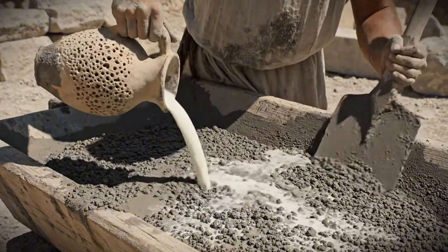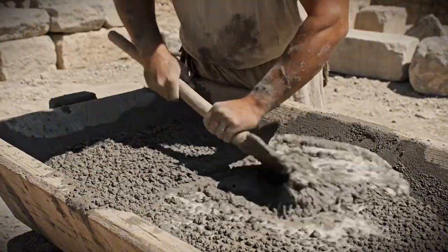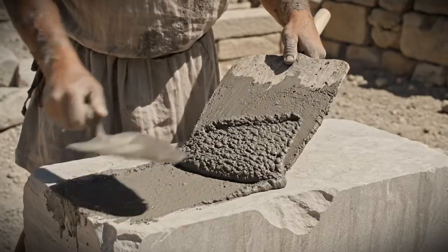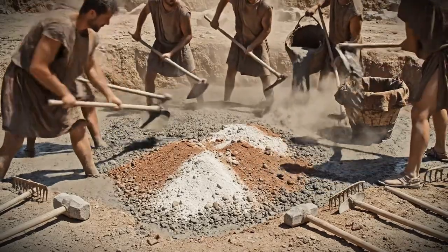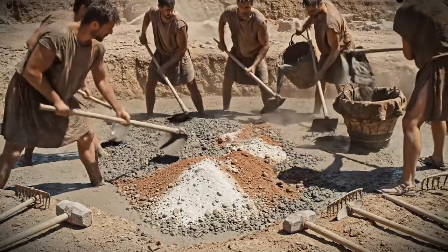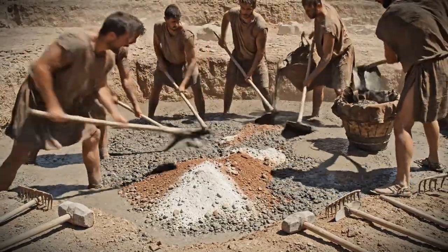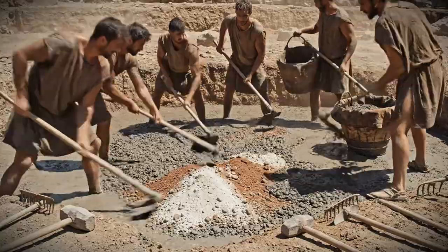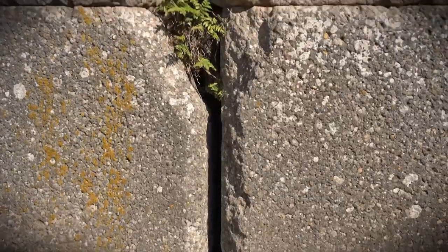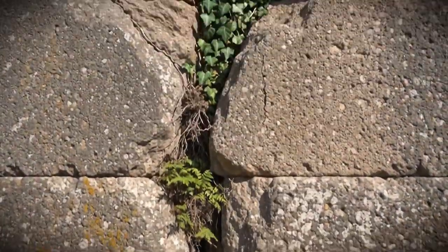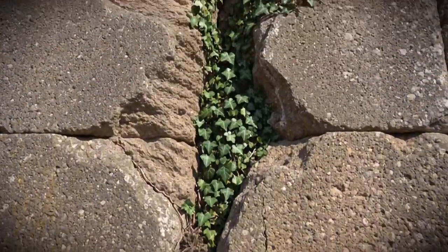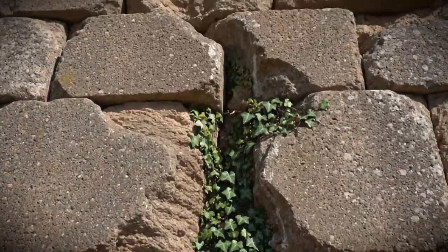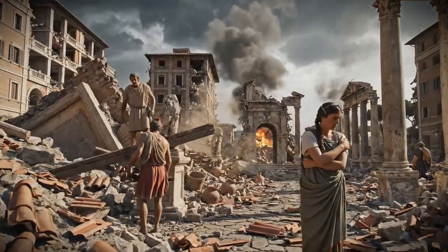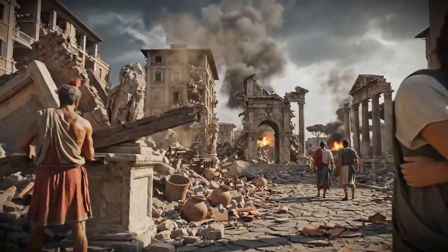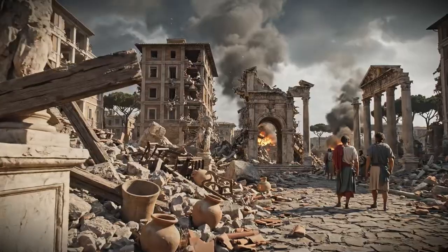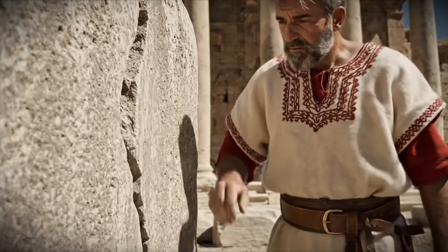But unlike modern concrete, which completes this reaction relatively quickly and then begins a slow decline, Roman concrete containing pozzolana continued reacting for centuries. The presence of aluminum in the volcanic ash created additional compounds, tobermorite and phillipsite, that filled microscopic cracks as they formed. This is the genius of the design. The concrete didn't just endure damage, it actively repaired itself through ongoing chemical processes.